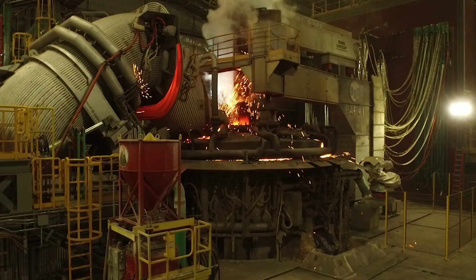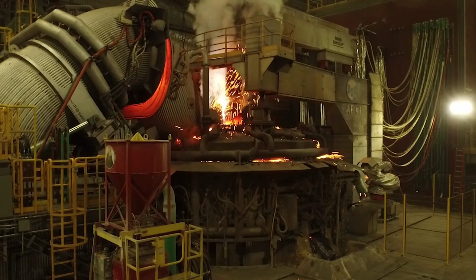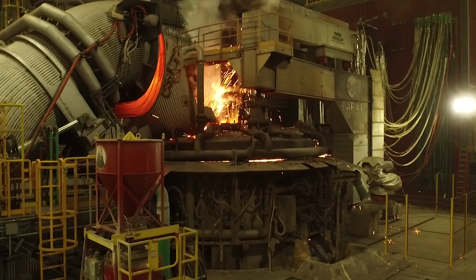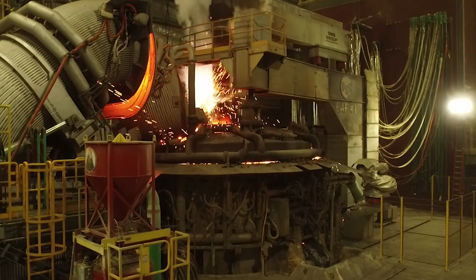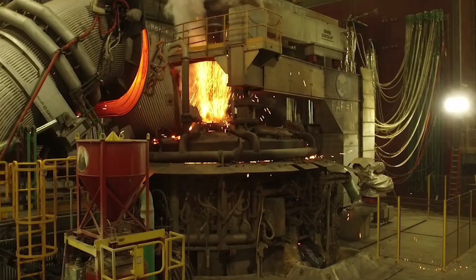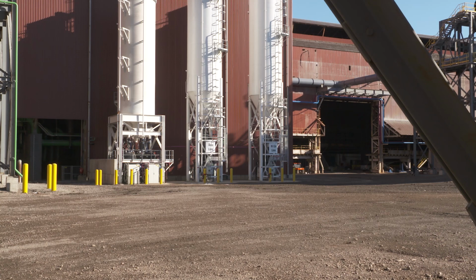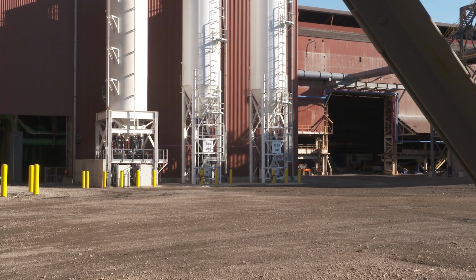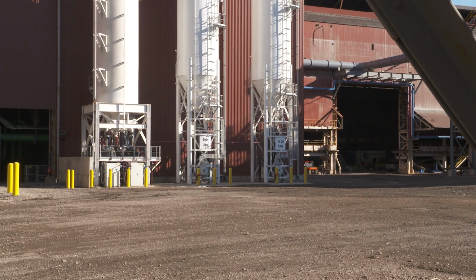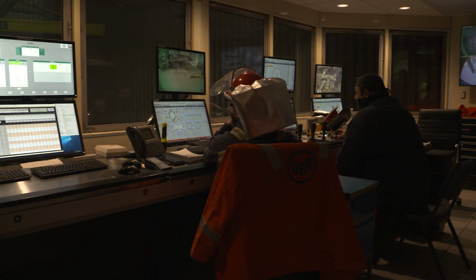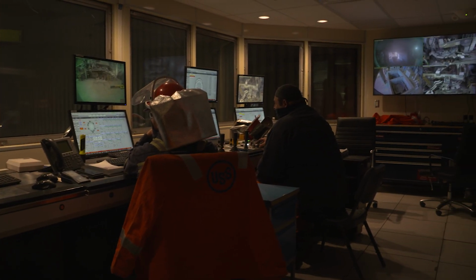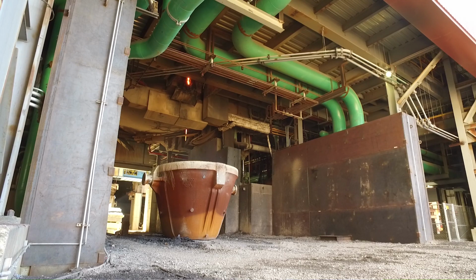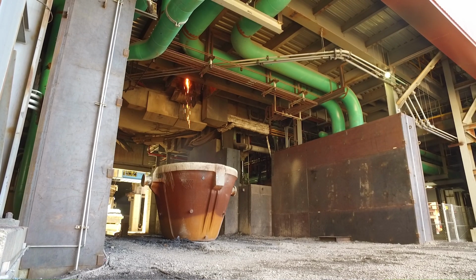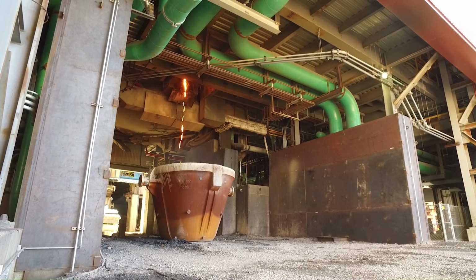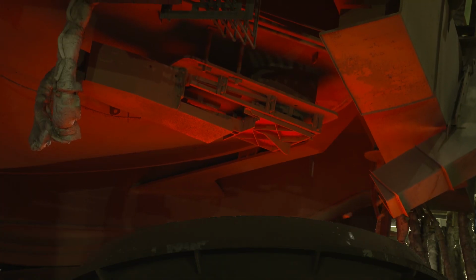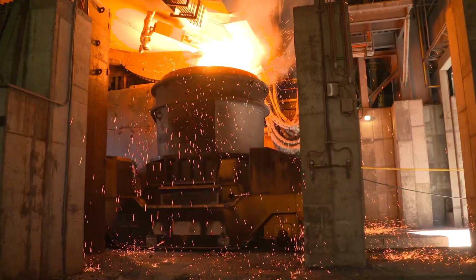Additionally, 8 burners that use oxygen and natural gas are used to speed melting. To introduce this incredible amount of energy into a 25-foot diameter shell is truly like capturing lightning in a bottle. Lime and carbon are injected through the sidewalls to refine the steel until the temperature reaches about 3,000 degrees. Employees operate the furnace from a pulpit and take temperature and chemical composition tests. Slag, which are impurities, are decanted into a slag pot where it'll be recycled. And then an aperture will be opened and steel will flow through a tap hole into a ladle.